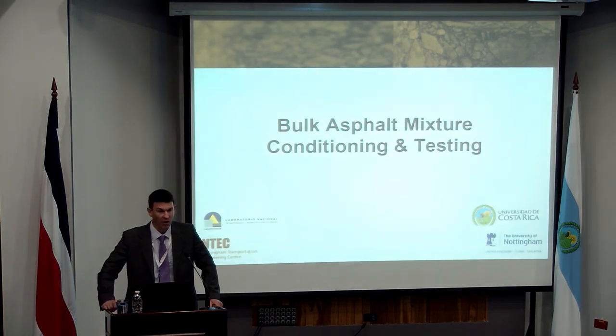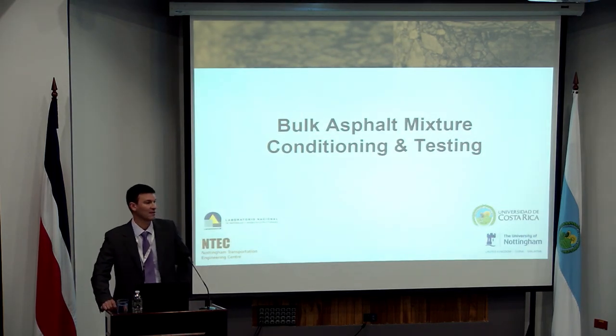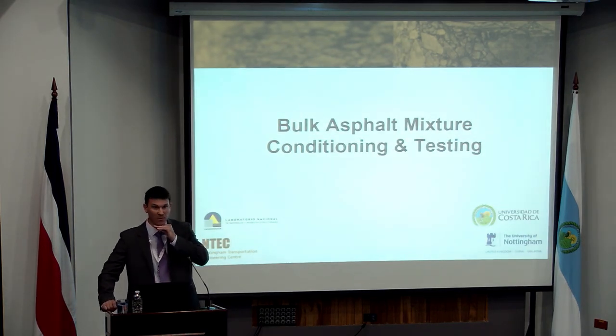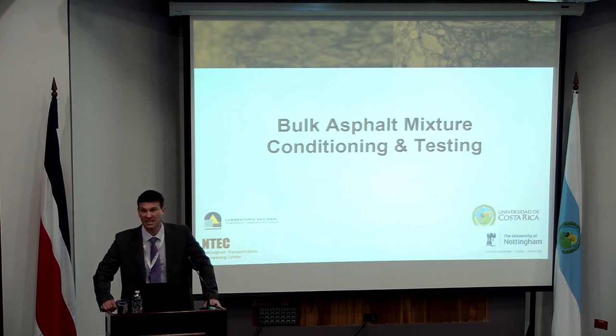So the last thing we wanted to do then was to link the bulk properties. So far we've looked at surface energy, we've looked at intrinsic adhesion, we've looked at a practical way of measuring adhesion. And I did mention, obviously, there are other techniques. We talked about the PATTI, but the peel test tended to give us very reliable, very repeatable, and very useful results that we actually then could correlate with particular materials in the field.